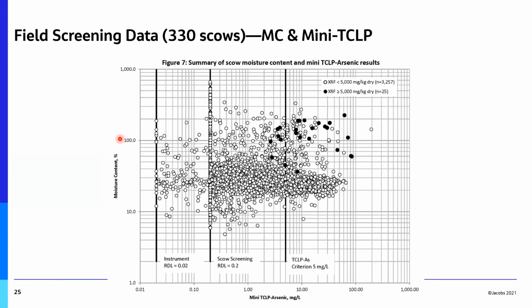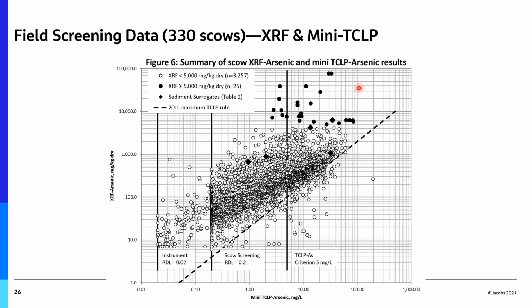This is the moisture content, right from the scow as a function of the Mini-TCLP and our detection limits and our TCLP criteria. We had 2 correlations, as I showed you, for the XRF. The one that was over 5,000 was really for the soft dredge materials. So I'm showing you what those actual points were that were probably really soft SDM. And then most of the rest of the values were basically below 3,000 when we had our correlation change.